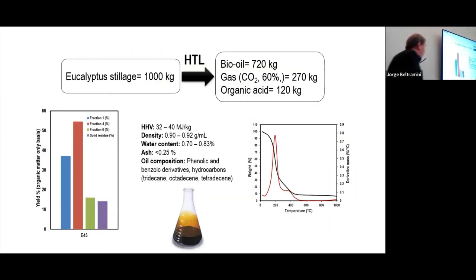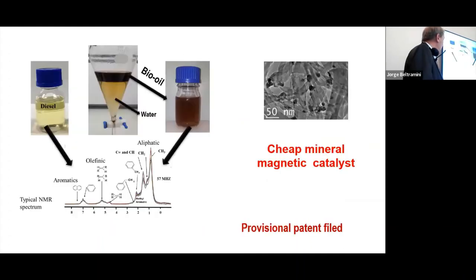This is an example of eucalyptus spent stillage. This is a bio-oil that we produce from 1,000 kilos of that material. We produce 720 kilos of bio-oil, 270 kilos of gas, and 120 kilos of organic acid. The three fractions can be reused. And what is important is that this is the composition of the bio-oil. We do the fractionation and we get a diesel type. We are using a cheap magnetic catalyst. We also filed a provisional patent.